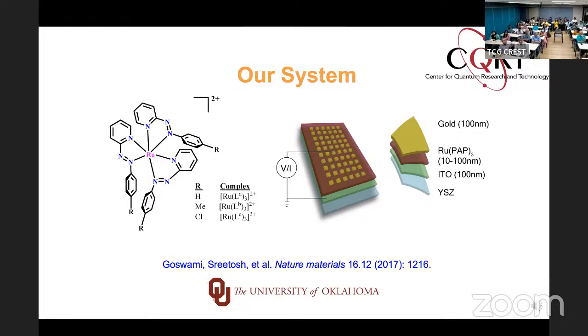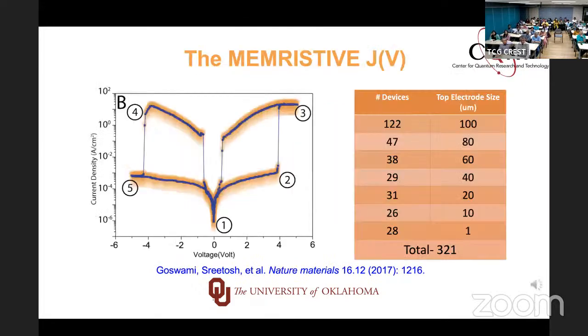So we just spin it on top of a bottom electrode of ITO on YSZ, and then the brown material is your molecule, and then we put a gold electrode on top. So it's a simple capacitor structure. We look at the vertical transport of this stuff, and when you do that, you get this remarkable switching characteristic.